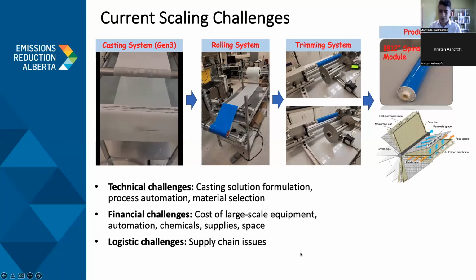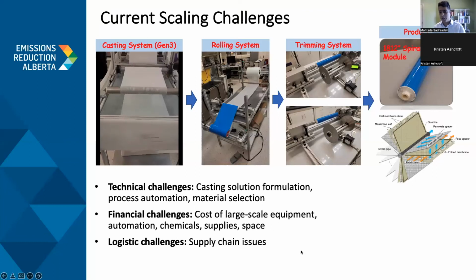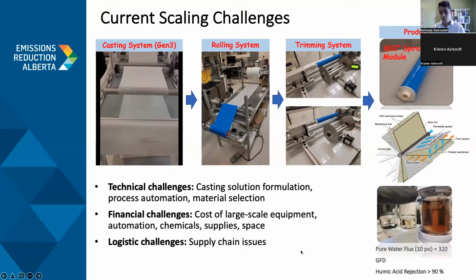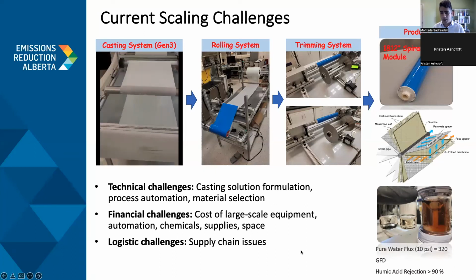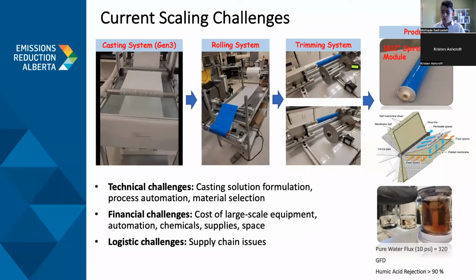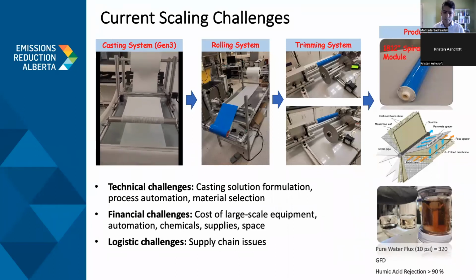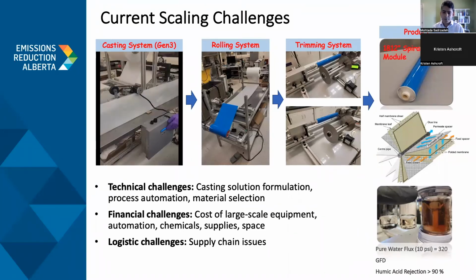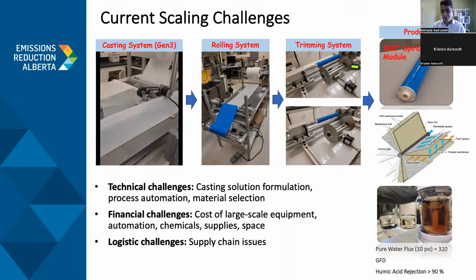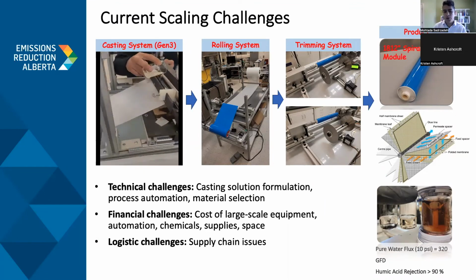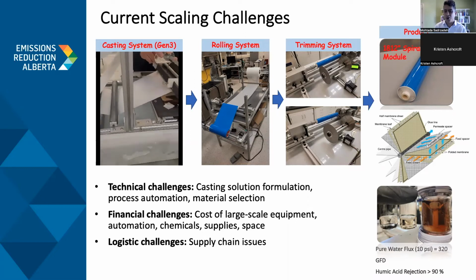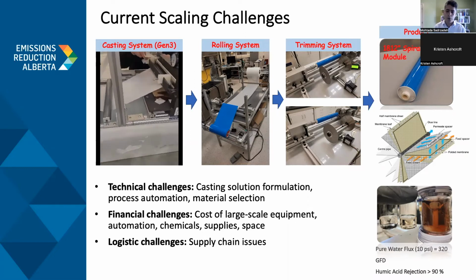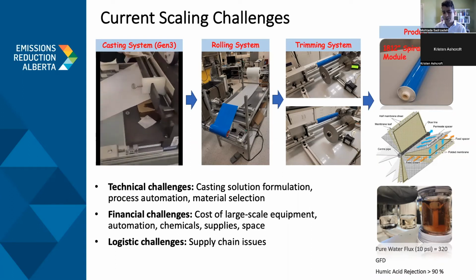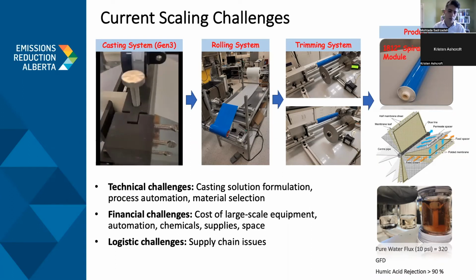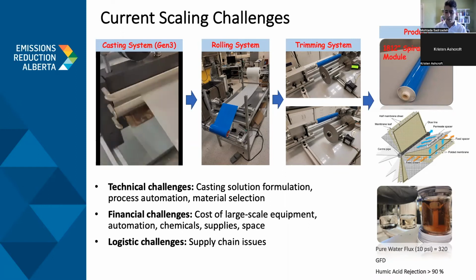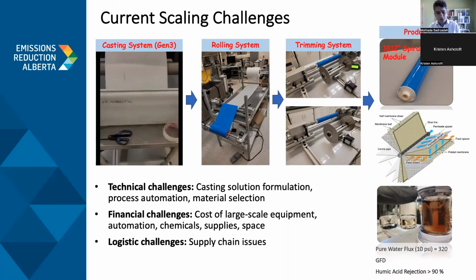The preliminary tests showed that this membrane can separate humic acid from wastewater by more than 90% rejection, and the flux is as high as 320 GFD. The technical challenges related to the casting solution formulation and manufacturing process design are already resolved in our lab. We predict some financial and logistic challenges for the mass production of these modules using a larger scale, fully automatic process. Next slide, please.